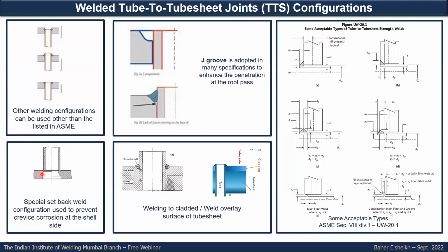tube-to-tube sheet weld, where it is welded to the back side of the tube to avoid any crevices between the tube and the tube sheet hole. Or one of the common recommendations, instead of the normal V groove, is to apply a J groove. J groove, if you can see here, or U groove, compared to the normal V groove, you have a better chance to have full penetration of the root pass, especially for such small sizes of joints.